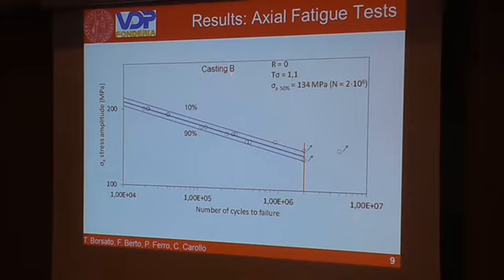In the case of casting B, there is a higher value of the stress amplitude at 2 million cycles and a survival probability of 50%, with a narrow scatter band and a lower scatter index equal to 1.1.